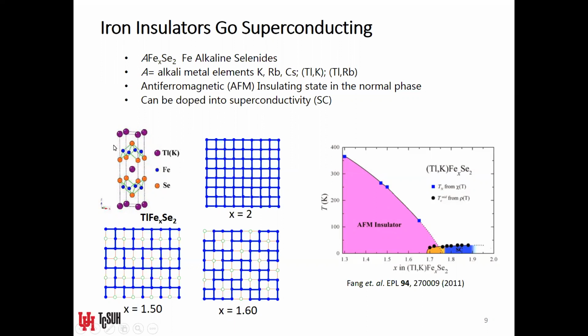So here you'll see, for example, our good old iron chalcogenide plane here. And then the blue lattice is meant to represent iron plaquettes. Okay, so as you get to about 1.7 in the vacancies, and this is shown over on the phase diagram, you enter this superconducting phase. Okay, so this iron alkaline selenide is a nice insulator. There's no question, if you do an experiment and you measure bulk properties, this is an iron insulator. This is one of the first examples of where it was shown that you could actually take an iron insulator and drive it into the superconducting phase along the same lines or philosophy as you would a cuprate.